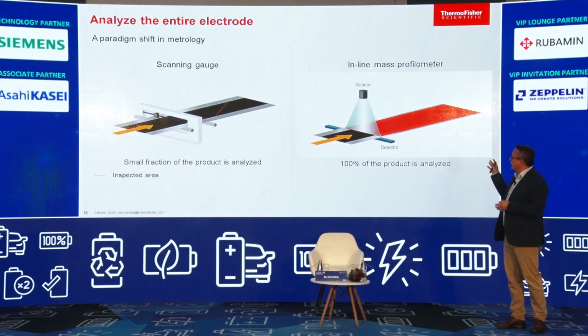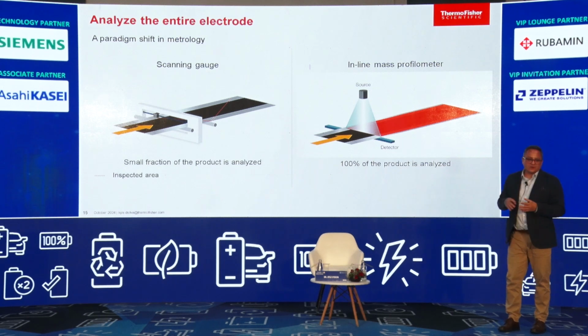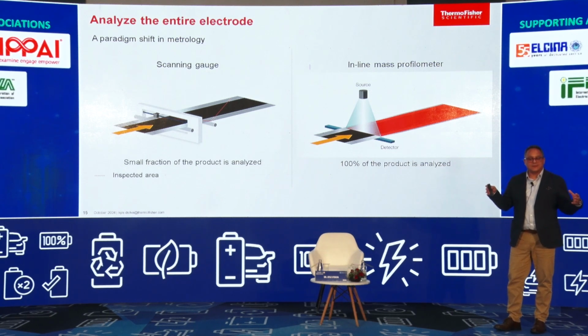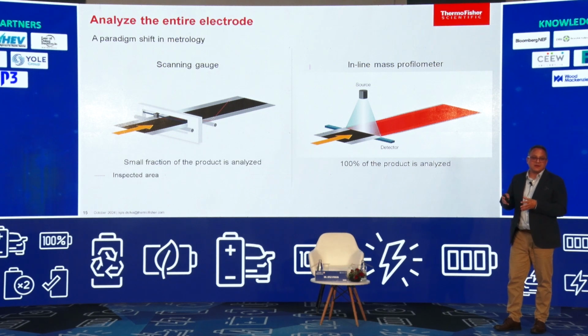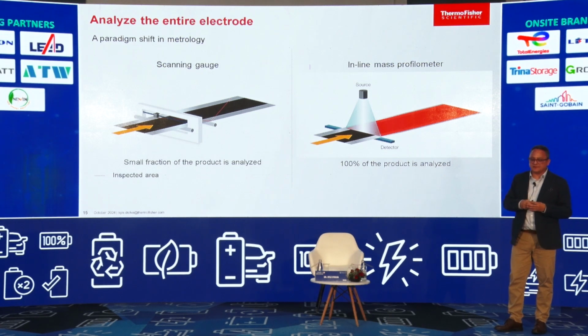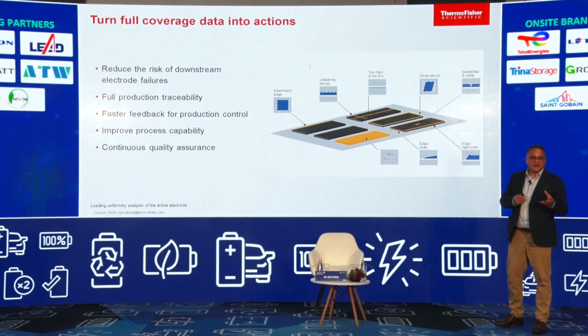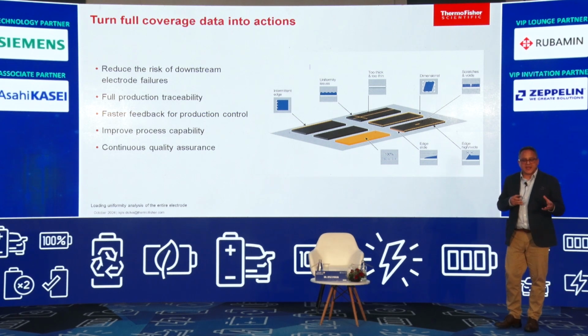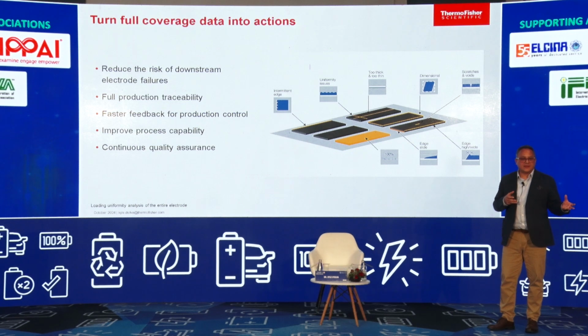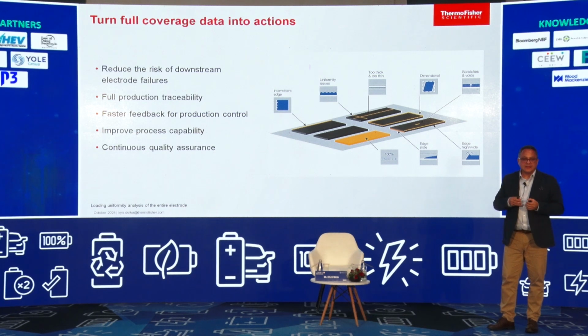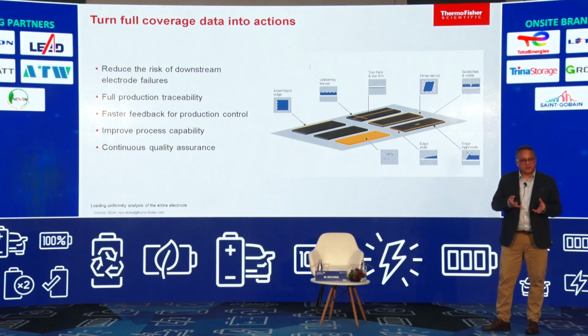So with our new system for the mass profilometer, we use an X-ray based source and measure across the entire width of the system and detect using a complex array of sensors. This allows us to measure the material moving at fast speeds, up to 100 meters per minute, and measure 100% of the coated material. It facilitates you seeing defects that you wouldn't be able to detect through other processes. You can take a look at the edges of patches. You can look at bleed of the active material at the edges. You can look at what's called bunny ears, thick patches at the edge of the material. Ripples, voids, scratches, defects can all be detected using this novel technology.